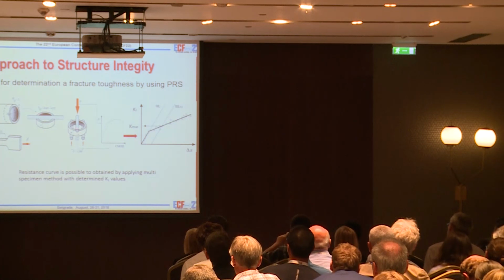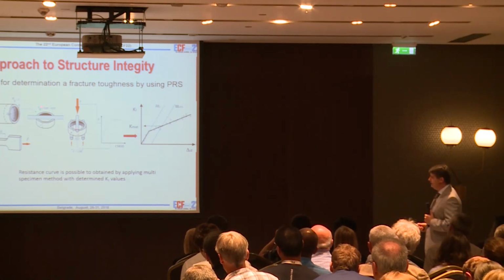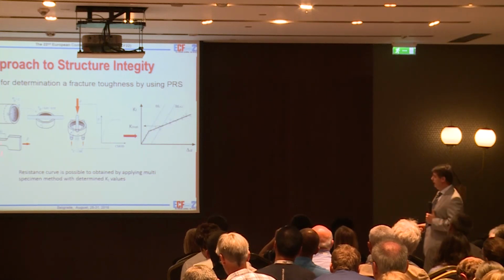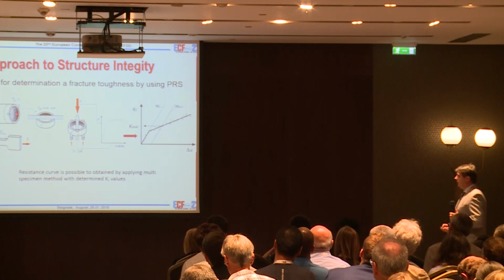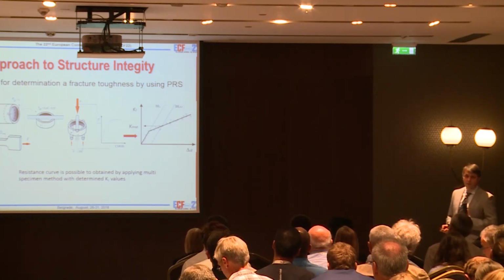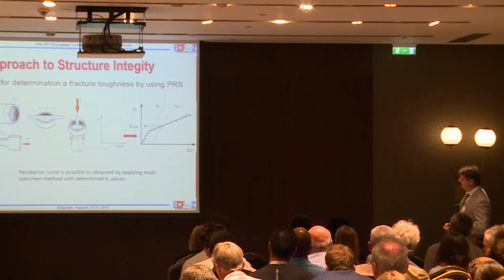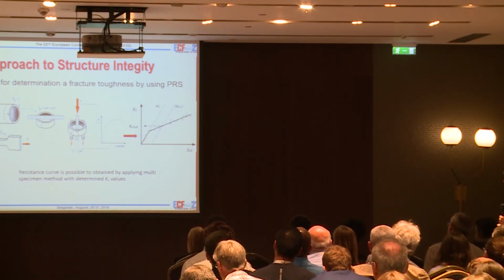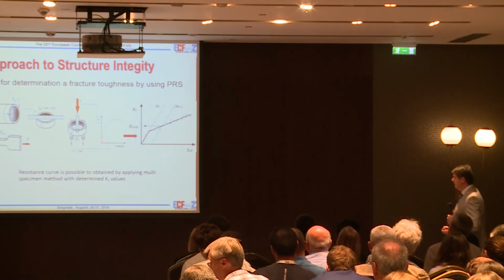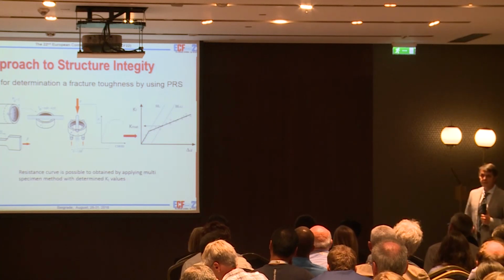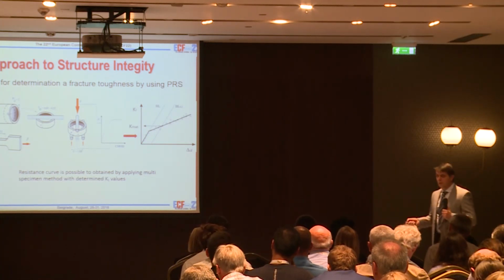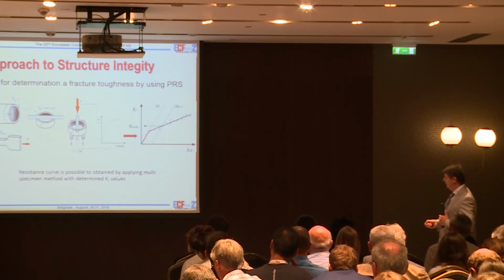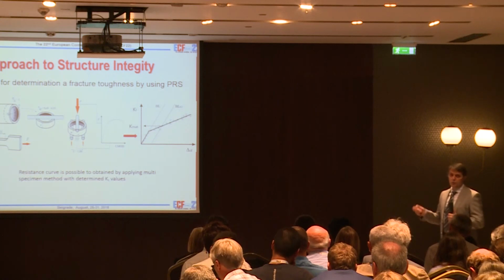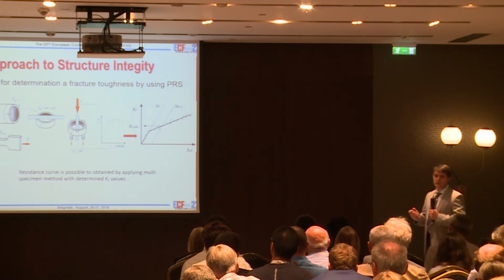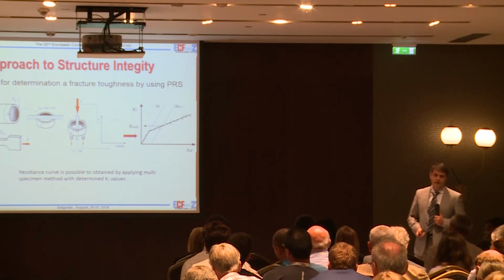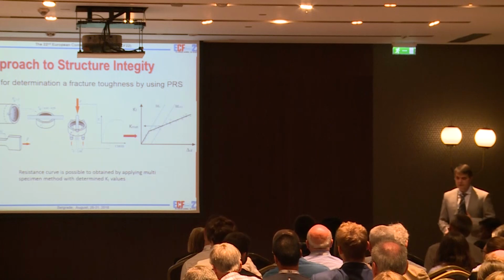So, how to apply this in the structure? It's actually easy. You need, of course, to do a tensile test, and you need to cut the ring. The ring should be double the thickness of the wall, and then you can make the notch, and then in the test you should record the amount of displacement, and when you get this curve, by applying these stress intensity factor values, you can also get the point values along the extension. If you are, for example, doing multi-specimen methods with different extensions, you can put in the line and tentatively estimate the stress intensity factor.